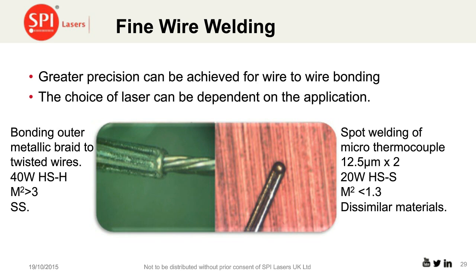The example on the right-hand side, however, is joining of two micro wires that are only 12.5 microns in diameter. This particular application is for a micro thermocouple. It's a similar application, but to hit that tip, you need a very fine spot, and this is achieved with a 20 watt laser, truly single-moded, with an M squared of less than 1.3.